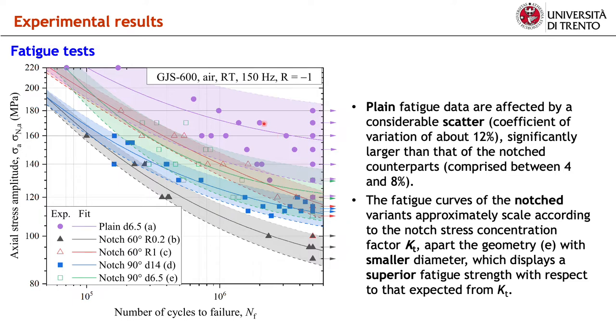The results of the axial fatigue tests are compared in this plot. It can be noted that the plain fatigue data are affected by a considerable scatter, significantly larger than that of the notched counterpart. The S-N curves of the notch variants approximately scale according to the notch stress concentration factor Kt, apart from geometry E, which displays a superior fatigue strength with respect to that expected from Kt. Apparently, the small specimen diameter results in a more localized and thus less detrimental notch stress field.